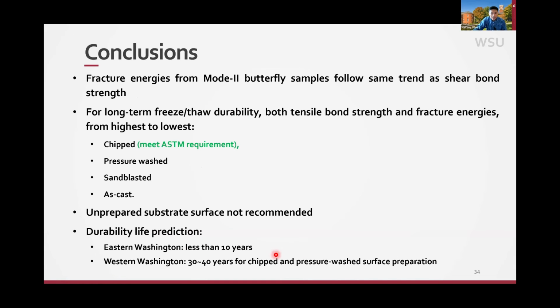And then the fracture energies from the mode 2, the butterfly, pretty much follow the same trend as the shear bond strength. In terms of the freeze-thaw cycles and durability, we saw the chipped method surface preparation give you the best durability and meet that 60% retained strength if you use the chipped method, while the other methods didn't meet that standard. So definitely we would recommend that you prepare the surface.